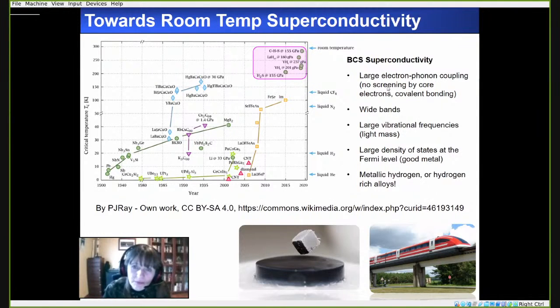It was speculated already a long time ago by Neil Ashcroft that metallic hydrogen could be a high temperature superconductor within BCS theory because of the large electron phonon coupling, no screening by core electrons, and the covalent bonding. Moreover, the BCS superconductors are suggested to have wide bands, which would happen within the hydrogen under pressure. And hydrogen has large vibrational frequencies due to its light mass, and it would have a large density of states at the Fermi level. However, in experiments, it has been really difficult to metallize hydrogen, and so far superconductivity has not been measured in a sample of hydrogen compressed to very high pressures.